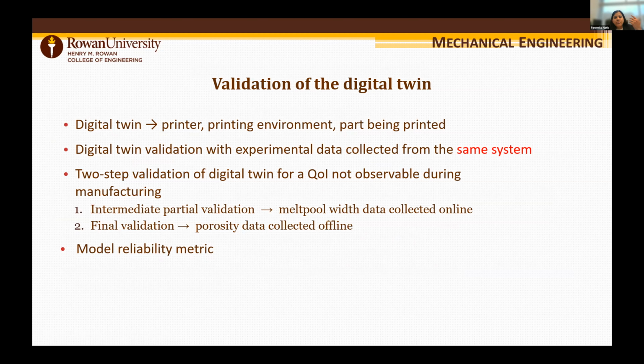Which then finally brings me to the validation of the digital twin. Now, a digital twin is specific to the printer, the printing environment, and the part being printed. So when we need to validate the digital twin, the experimental data has to come from the same system. Here we do the two-step validation of the digital twin because our quantity of interest is not observable during manufacturing. So we do the intermediate or partial validation using the melt pool width, by using the data that we collected online, and the final validation is when we collect data offline after the part has been printed. And here again, we use the same model reliability matrix to do the validation.